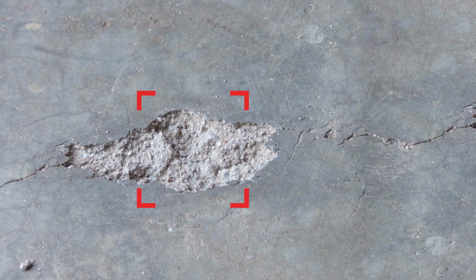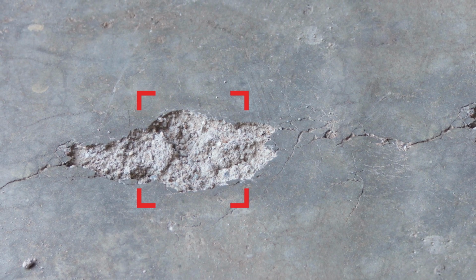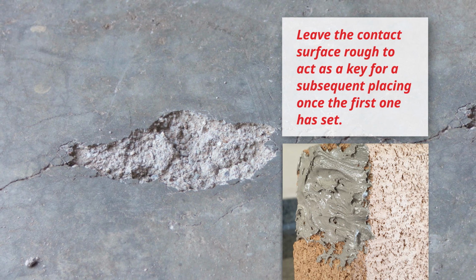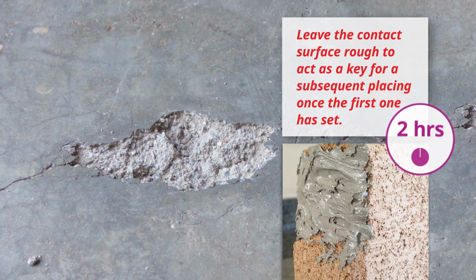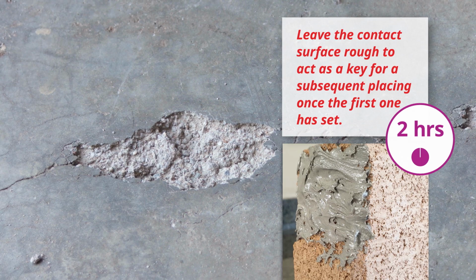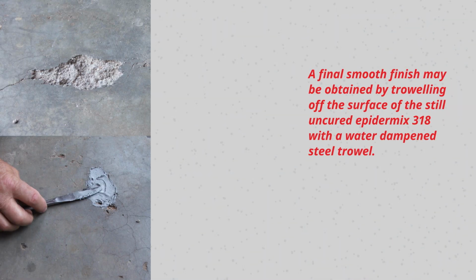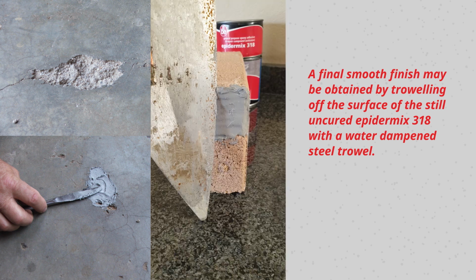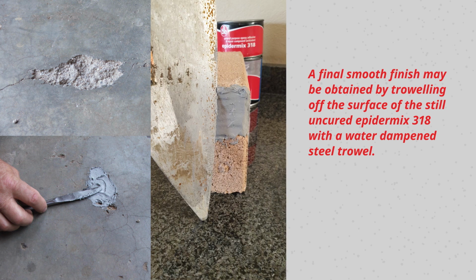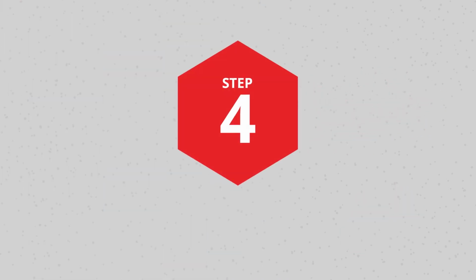If the volume is too big to repair in one placing, leave the contact surface rough to act as a key for a subsequent placing once the first one has set. A final smooth finish may be obtained by trowelling off the surface of the still uncured Epidermix 318 with a water-dampened steel trowel.